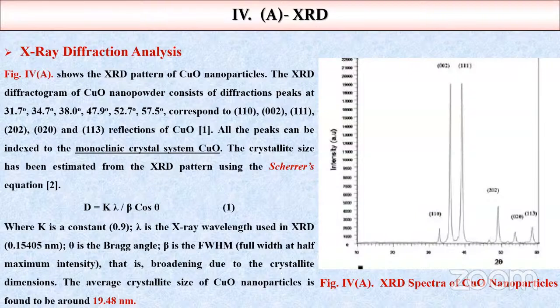Here, this figure shows the XRD spectra of copper oxide nanoparticles. So this X-ray diffraction analysis shows the XRD pattern of copper oxide nanoparticles. The XRD diffractogram of copper oxide nanopowder consists of diffraction peaks at these different degrees, which correspond to the 110, 002, etc. reflections of copper oxide. All the peaks can be indexed to the monoclinic crystal system.